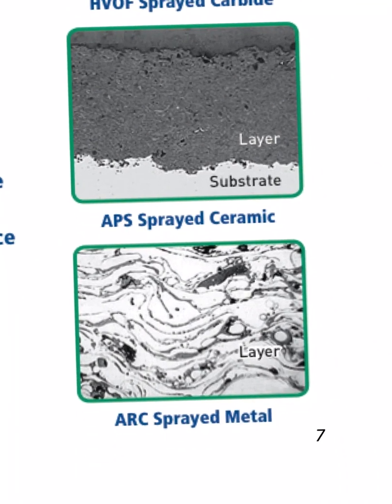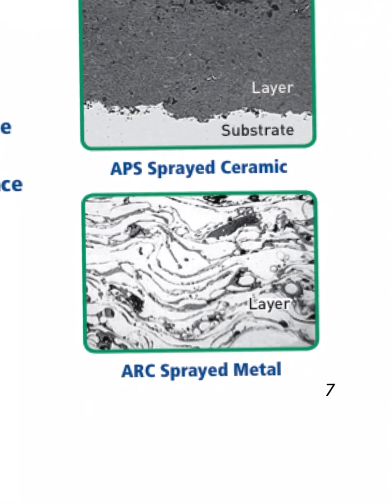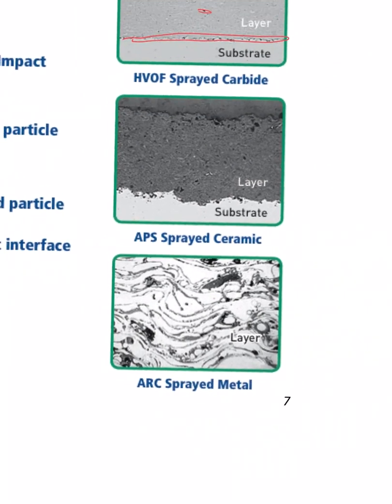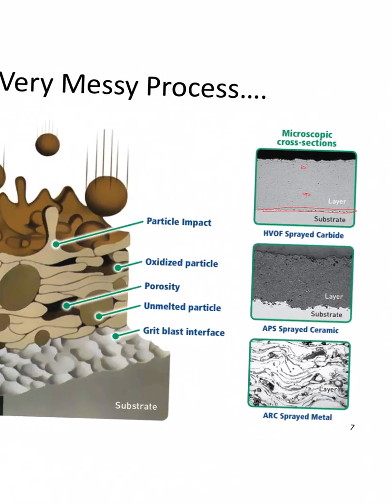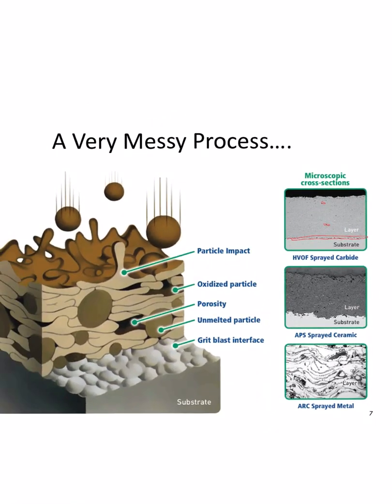And then for this one example of a plasma sprayed metal, you can start to make out what we just saw in that cartoon, which is the tree ring effect of this. Every layer leaves its evidence there as they hit, cool off, and then another droplet arrives maybe later as this thing's spinning around, all right, and you get this type of layering effect. So it's like tree rings, essentially. You can tell what the thermal history of the implant is by looking at its microstructure.